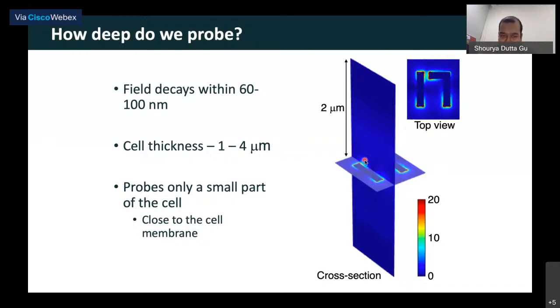So what this is telling us is we are only enhancing the molecules that are that close to the structure, only between 60 to 100 nanometers. Now, if you compare it with cells, cells have a typical thickness of 1 to 4 microns. So what you're actually measuring is not the whole cell, you have to remember. You're measuring only something which is very, very close to the cell membrane, right? And that is precisely what we use for the diagnostic purpose.